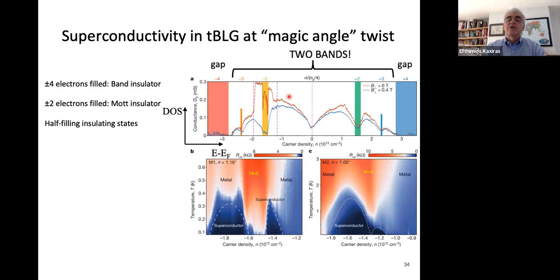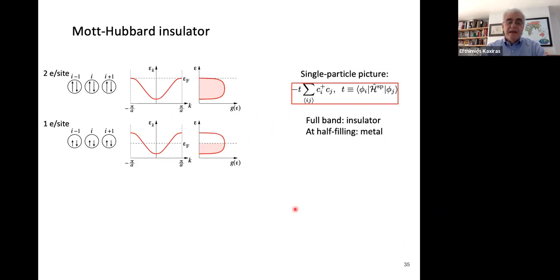This is the range where the two bands should appear. But then you have additional gaps in the middle of the bands. And there's no way that band theory can account for that. So basically what this picture suggests is that there's a breakdown of band theory.